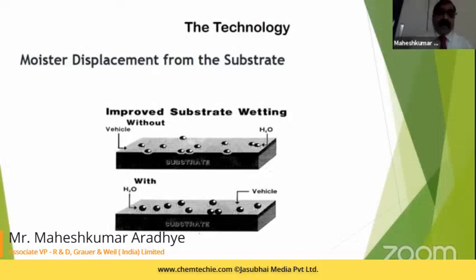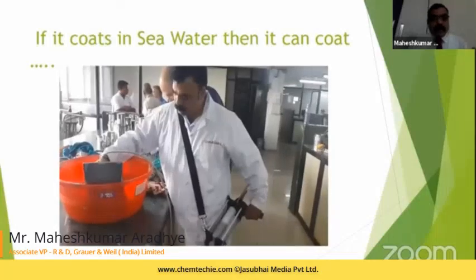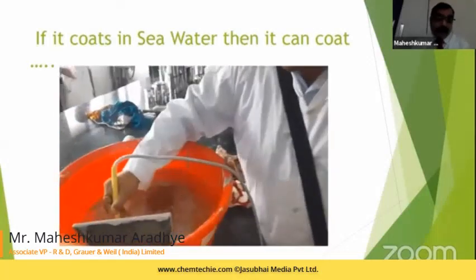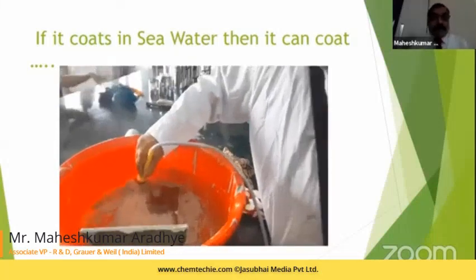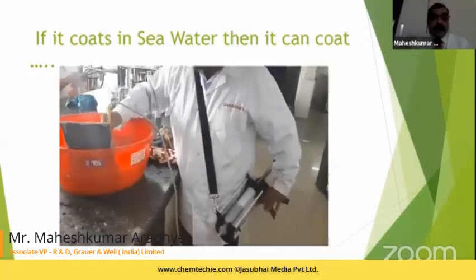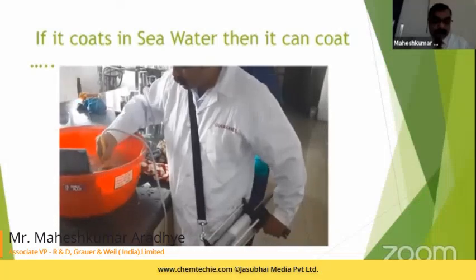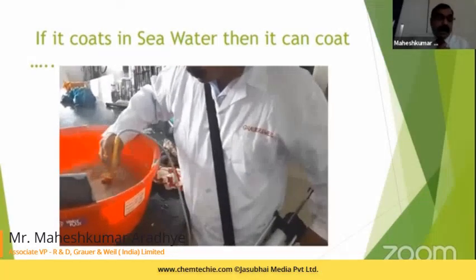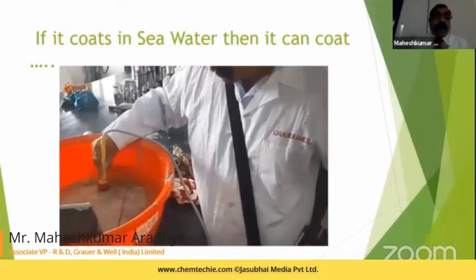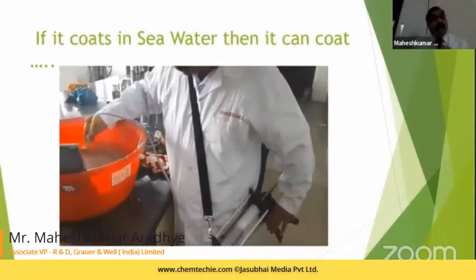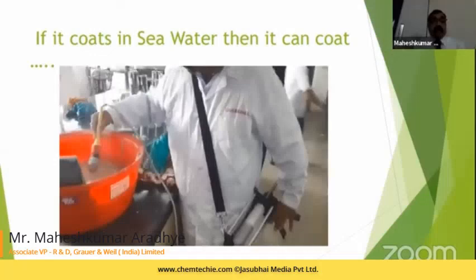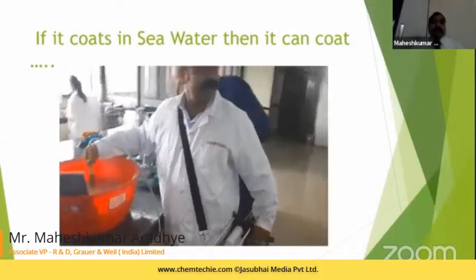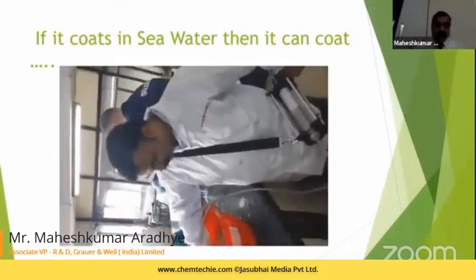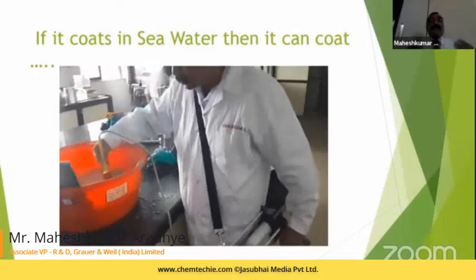I think explaining it with a slide may not give you the correct understanding. Let's have a look at how it displaces moisture and gets applied onto the surface. You can see here, I'm applying this coating in seawater. There is an abundance of water, and in this water I'm able to reach the substrate with the help of plural component equipment, and I'm able to apply a coating very easily without any problem onto the substrate, even though a whole lot of water, and that too seawater, is present. Now just tell me, if it can coat in seawater, then it can coat any substrate anywhere.